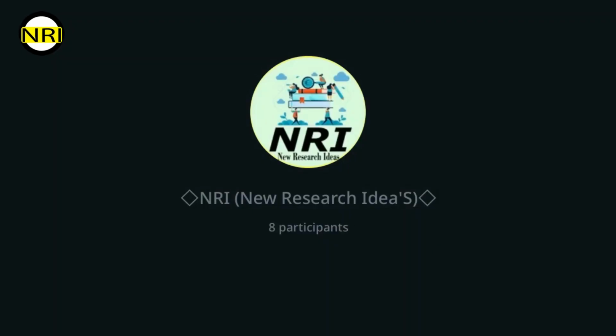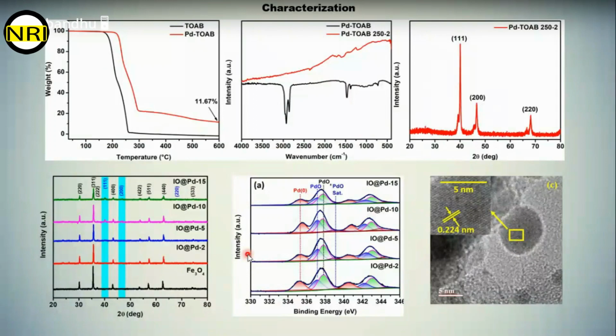After that, we wanted to know what oxidation state of palladium is present in the sample. That is why we measured the X-ray photoelectron spectroscopy of the samples, and this is the palladium XPS. We can see two doublets of peaks here. One is for palladium nanoparticles, and another is for palladium oxide, palladium 2 plus. But you can see this palladium 2 plus peak is broader than the palladium 0 peak. That's why we deconvoluted this palladium 2 plus peak into two. The other peak is due to a higher oxidation state of palladium oxide.